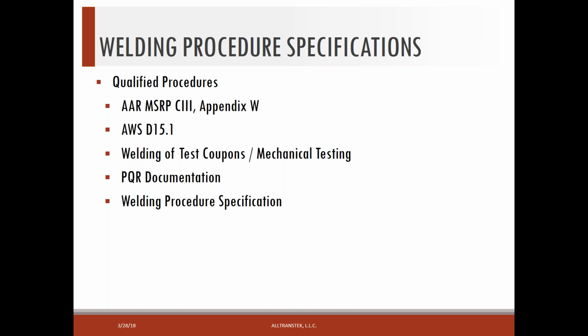If we're welding in other areas, jacket welding, structural welding, we have the possibility, and again I use the term possibility, of using a pre-qualified procedure. We have to look at all the requirements that are in D15.1 for pre-qualified procedures and make sure that we're able to use a pre-qualified procedure. And if we don't meet all those requirements that are listed, then we have no alternative but to qualify the procedure.